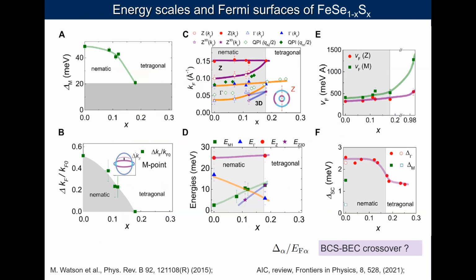And the superconducting gap determined by STM by the Hanaguri group is up to about 2 milli-electron volts. This type of ratio between having low Fermi energies and a superconducting gap has also been proposed that in some systems, there may be conditions for the BCS-BEC crossover.